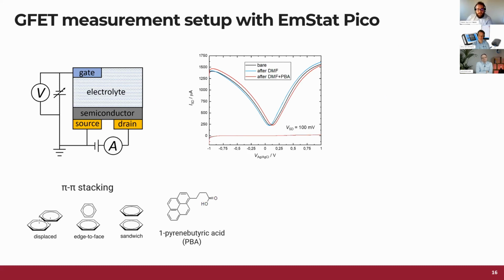And then we immerse the whole device into DMF, which is a common solvent for pyrenes, which are, again, those big organic molecules, hydrophobic. Only this tail COOH group is hydrophilic. So they do not like water that much when it comes to solubility. They like DMF, for example. So we perform the measurement in DMF after immersing in DMF, and we can see that there is a huge shift from the black curve to the blue one.